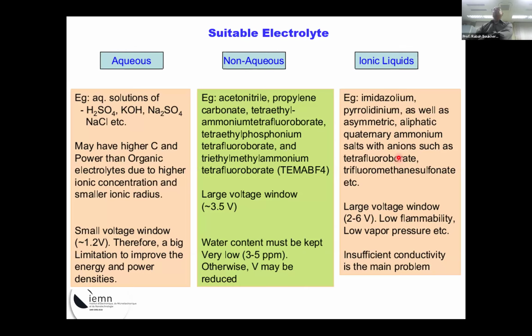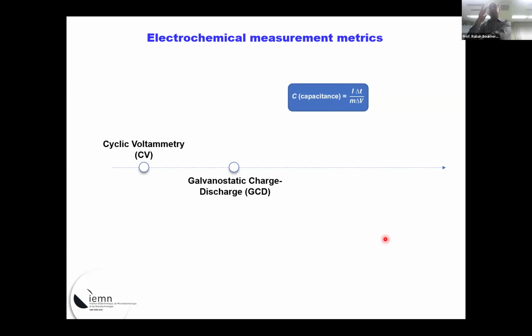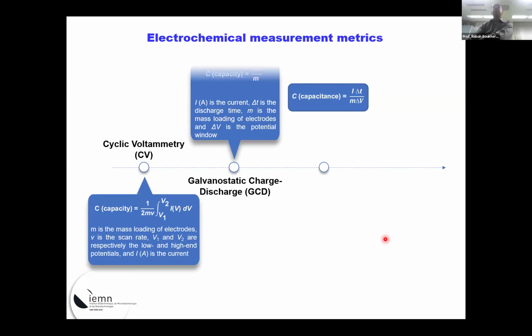Interestingly, you have what you call ionic liquids. People call them a green solvent, but they're really not green, because most of them actually are toxic. So one has to be careful indeed, depending on the chemical structure and composition. This could be really toxic. The advantage, they have a very large potential window. They're low flammable and low vapor pressure. However, this comes with some limitation, which is the insufficient ionic conductivity, and they're often quite viscous. But I will show later on that there are other alternatives for this, and they work very, very nicely.